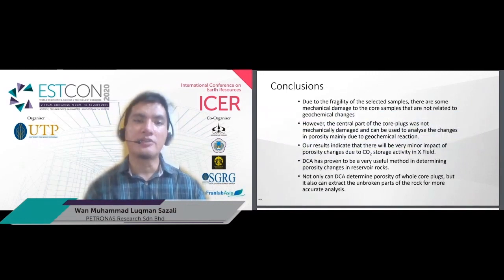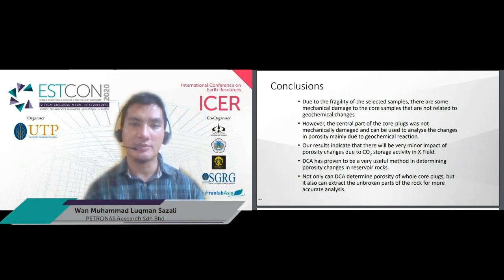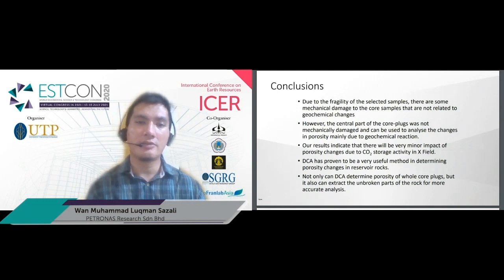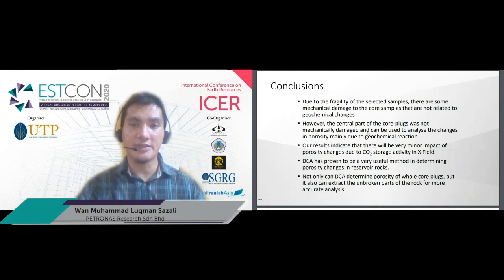In conclusion, due to the fragility of the selected samples, there is some mechanical damage to the core samples that is not related to the geochemical reaction. If we include this mechanical damage, it will not be representative of the geochemical changes that will happen during CO2 storage in the field later. Thanks to DCA, we were able to extract the middle part without mechanical damage and study the porosity changes happening due to geochemical reaction. Based on the result, we found that the porosity change is indeed very minimal and at lab scale does not have a major impact during CO2 storage in X-field.